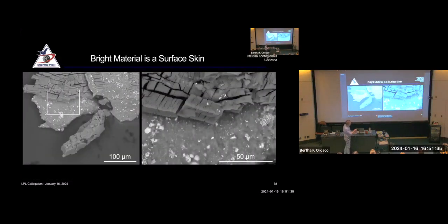It's highly fractured. It looks desiccated to me, right? Like it probably was a hydrated phase and it's lost its absorbed water and shrunk and fractured as a result of that. I don't know if that happened on Bennu due to surface exposure or just 4 billion years of time, or if this was something that happened after it arrived here on Earth, because it was under dry nitrogen. It still is under dry nitrogen. But to me, it looks really fragile, and just the way it fractured and broke here gives you a sense of it barely hanging on to the host rock that it's connected to.